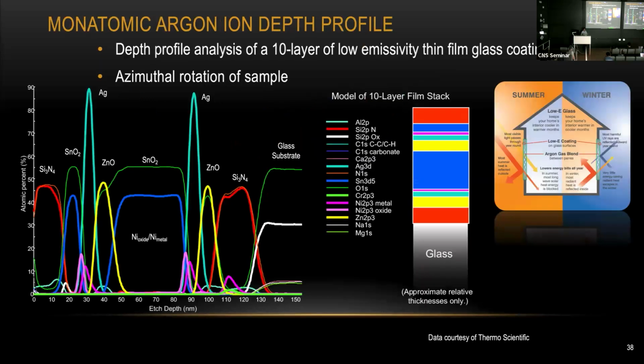And earlier I mentioned we can use a sputtering gun to do some depth profiling, and that's one example here. The sample is a so-called smart glass, which means you can keep your house warm during the wintertime and keep your house cold during the summertime. What's so special about this glass is that on top of the glass, there are actually multiple layers of coating. And you can use XPS to determine how thick each layer is and what kind of material each layer is. And sometimes also try to see any additional information in between layers.